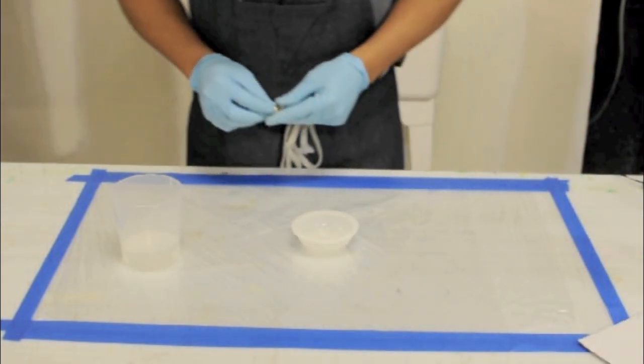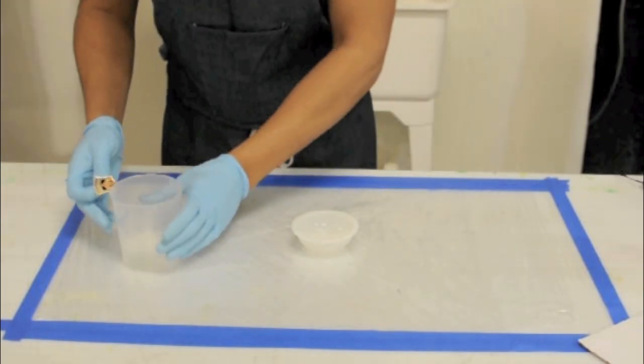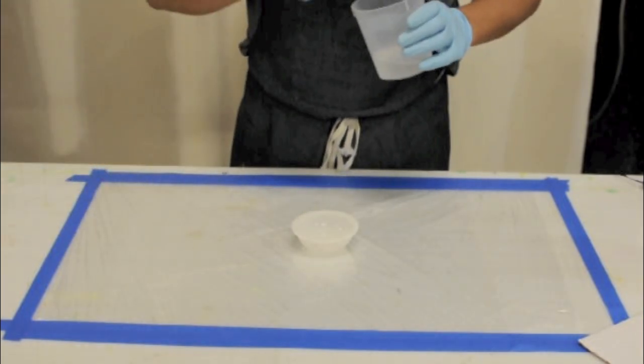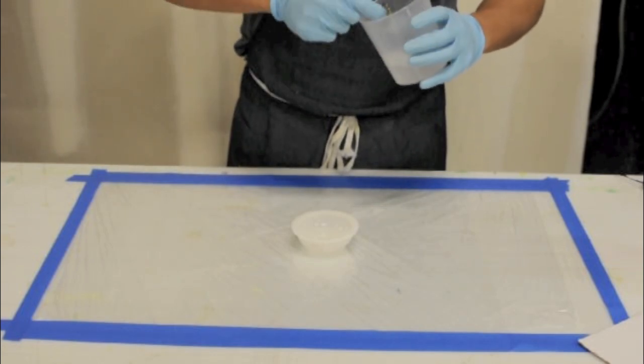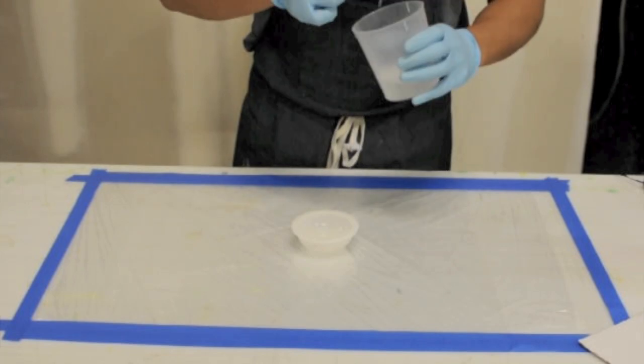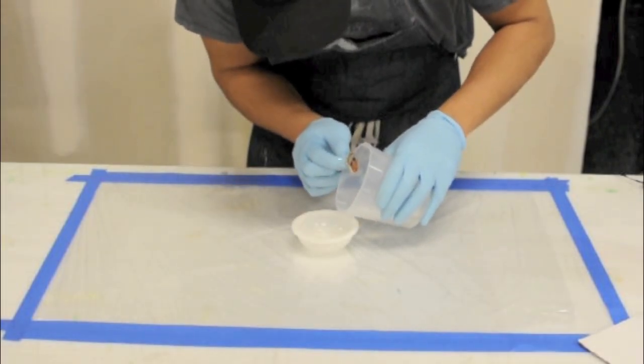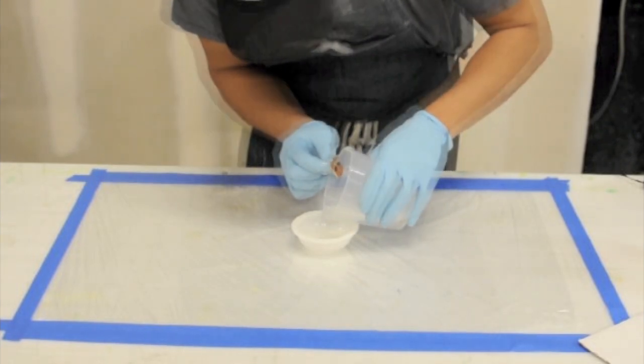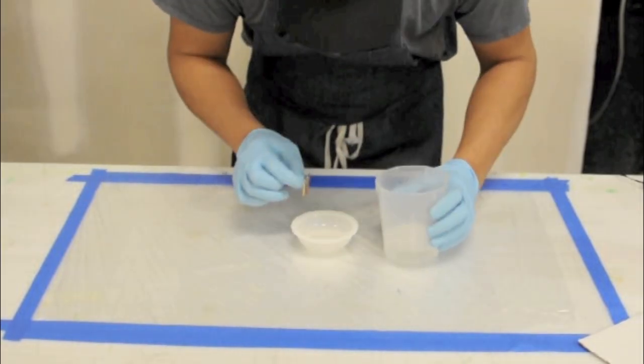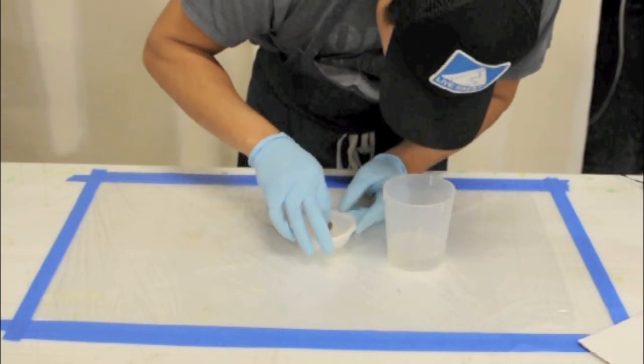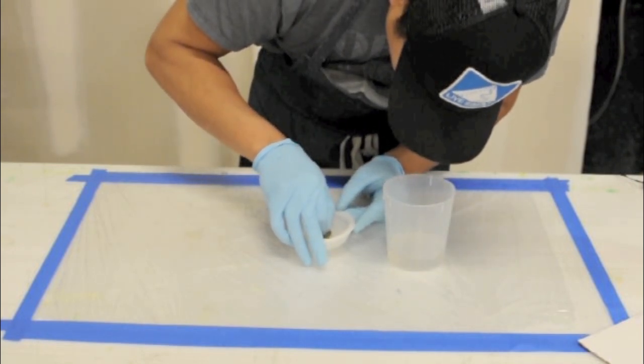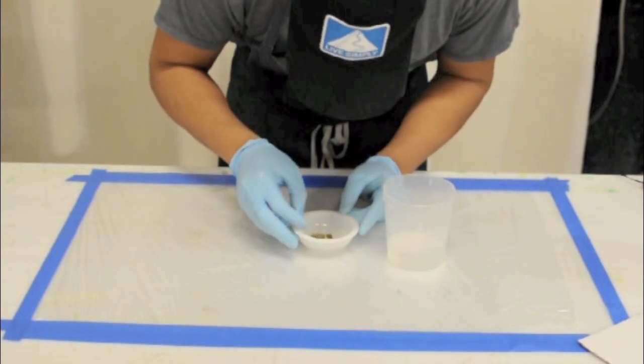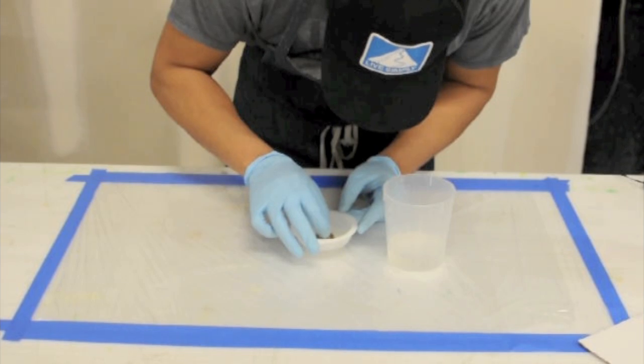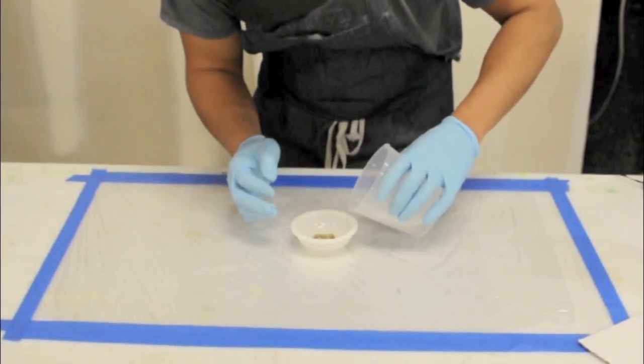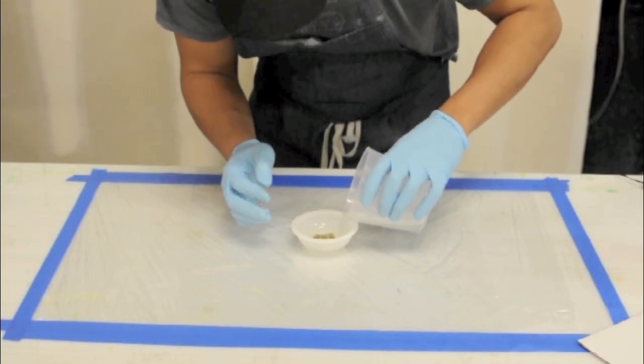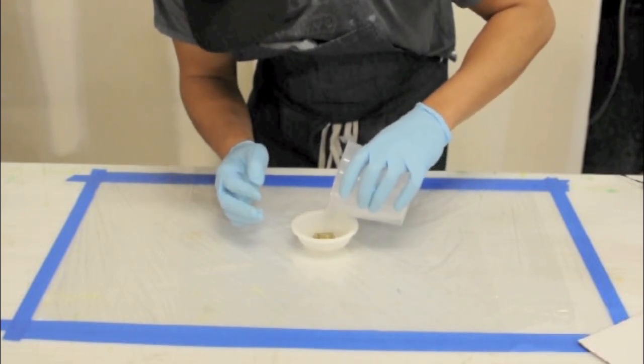There are several steps to make sure this is done properly. First, thoroughly wet the object you wish to embed with epoxy. Next, deposit a thin layer of epoxy over the previous layer. Now, carefully place your object, being sure not to trap any air bubbles between the object and the previous layer. Last, pour the remaining epoxy in this layer, cover your mold, and give it 24 hours to cure.